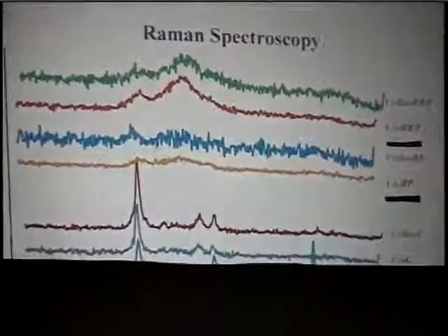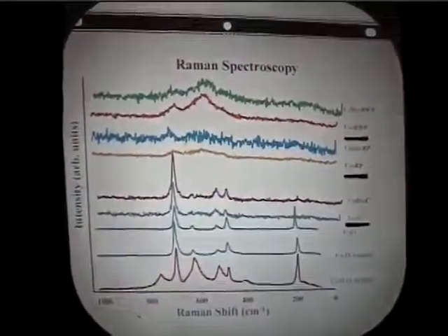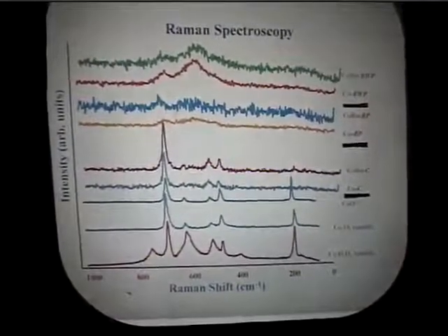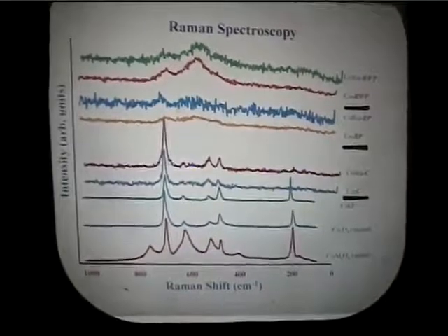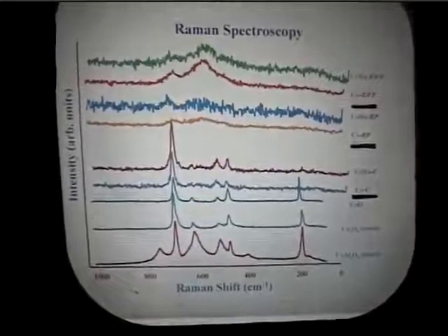And these are Raman spectra of the cobalt and cobalt ruthenium catalyst, the calcined sample, the reduced and passivated catalyst sample, and the reduced with the additional water vapor and passivated catalyst sample. Again, for references, Raman spectra of cobalt oxide, Co3O4, and cobalt aluminum spinel were also carried out here. As with the XRD results, after calcination, Co3O4 was present in both the cobalt and cobalt ruthenium catalysts. And after reduction, Co3O4 was reduced to cobalt oxide and cobalt metal, which can be seen by Raman spectroscopy.